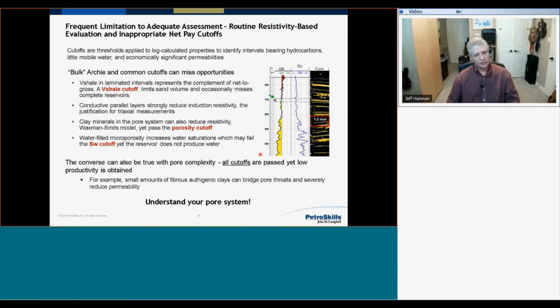But that may still pass the porosity cutoff. And we saw initially that some of those very fibrous or wispy clays, it doesn't take a large volume, may pass a porosity cutoff and not pass a permeability cutoff. Okay, and then there is water-filled microporosity, which will increase the water saturation and may fail the SW cutoff, and we saw a few examples of that, and yet the reservoir does not produce water. So this is the example I just mentioned with the fibrous clays: if we have clays blocking pore throats, all the cutoffs may be passed, yet we have low productivity.